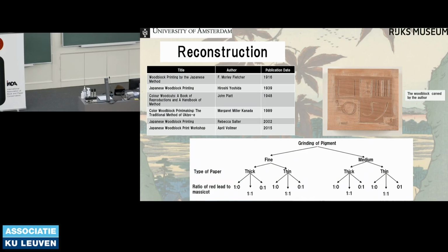For these variables, I created pigment mixtures of pure red lead, pure lead monoxide, and a 50-50 mixture of the two to test the effects of impurities. For the grind, I took the pigment as it was apparent from the manufacturer, and then I also created a second set that I ground further. And then for the paper, I simply examined the prints I looked at from the Rijksmuseum and found the thickest and thinnest papers apparent and found comparative in the collection of the Rijksmuseum.